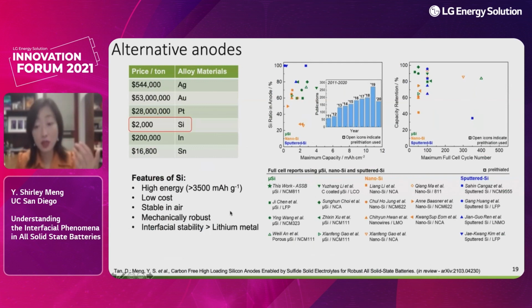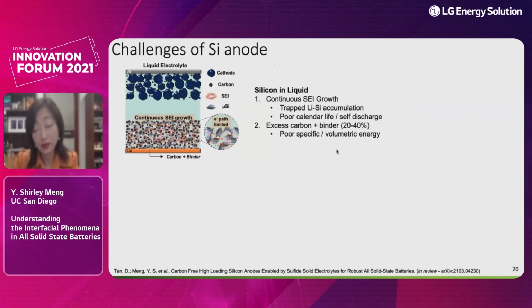So again, the advantage of having graduate students is, my student Darren Tan just thought: while everybody is doing carbon silicon composite, let's think about whether we really need carbon in the silicon anode. Because the literature survey shows there are hundreds of papers every year on silicon, however nobody has explored using 100% silicon in all solid state batteries to see what happens. So the hypothesis is very simple—I mentioned the non-flowing rigid mechanical property of the solid electrolyte. When we have liquid cells, the silicon will continuously break and the liquid will always flow into those cracks, and that's why the interface is very unstable for silicon.